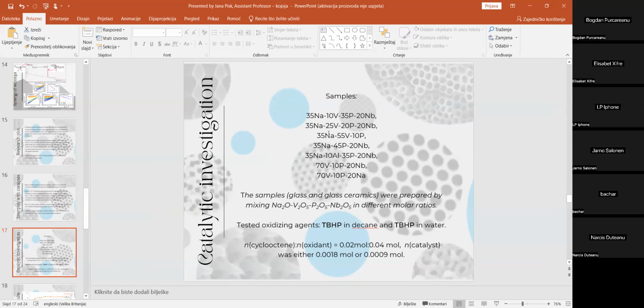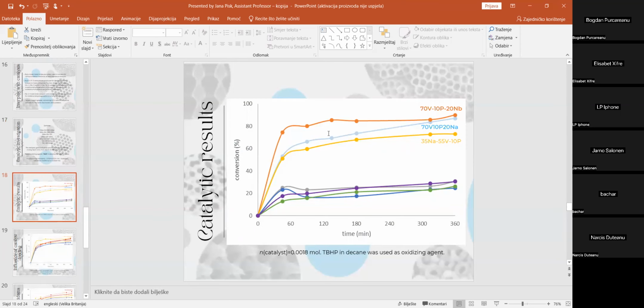The first test that we did, we wanted to test the reactions of cyclooctene epoxidation by using TBHP in decane and TBHP in water, and we wanted to compare those systems. Because from the previous results, we supposed that TBHP in decane should be the better oxidizing agent, and we didn't have any experience with these kinds of reactions. The first testing we did with the TBHP in decane, and the catalytic profiles are presented here. The three best materials for this kind of reaction contained a high loading of vanadium. And also, we can see that the samples with sodium and niobium have more or less the same activity at the end of the reaction, meaning after 6 hours.